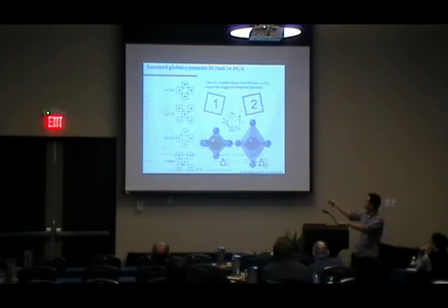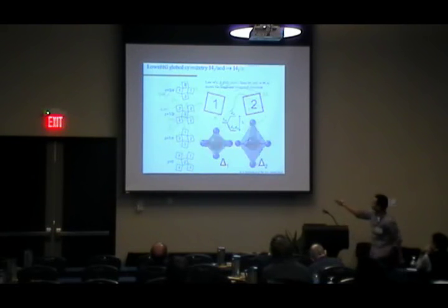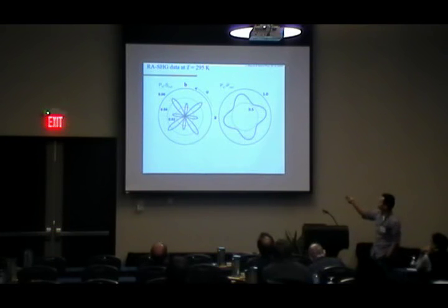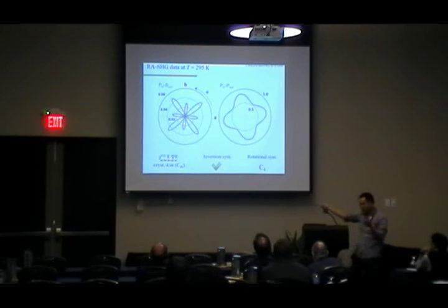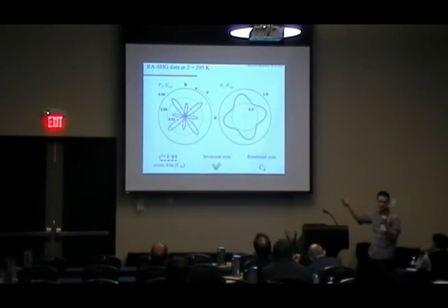Okay, so that was the crystallographic structure, which we concluded is due to this two sublattice tetragonal distortion of the oxygen octahedron. Well, let me now get to the important stuff. Those data sets I showed you were at room temperature, and this is a reproduction of just two of the polarization geometries, P in, S out and P in, P out. This is consistent with the I41/A space group, or the 4/M point group. It's inversion symmetric, and it's got fourfold rotational symmetry.